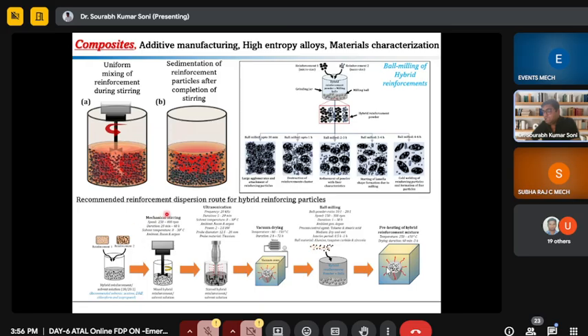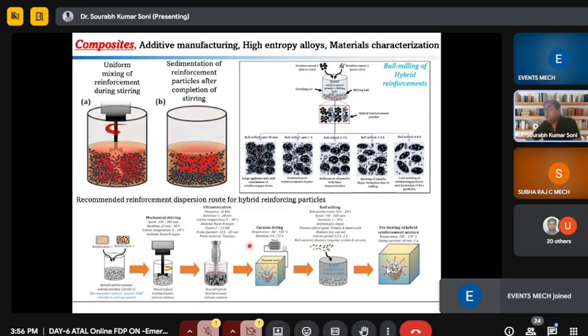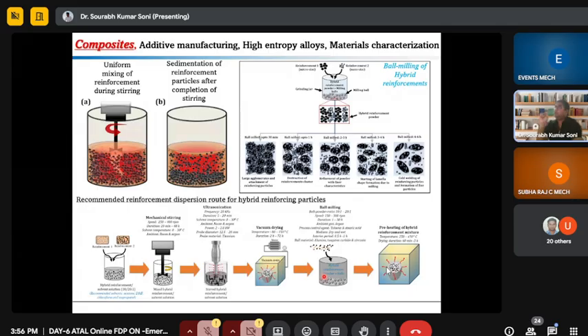So we'll do the mechanical stirring, then we'll do ultrasonication for a shorter duration. 20 minutes is very adequate, but after 20 minutes, it will destroy the morphology or microstructure of the reinforcement. Then vacuum drying. We must dry our reinforcement in vacuum, otherwise it will oxidize. And then we have to do ball milling for a shorter duration to mix uniformly, because one problem is there. If you do the ultrasonication, our powder is usually in wet form, not very dry. So first we need to ball mill, and then we have to preheat the reinforcement or hybrid reinforcement mixture before adding into the molten metal. So we will get a very good reinforcement mixture.